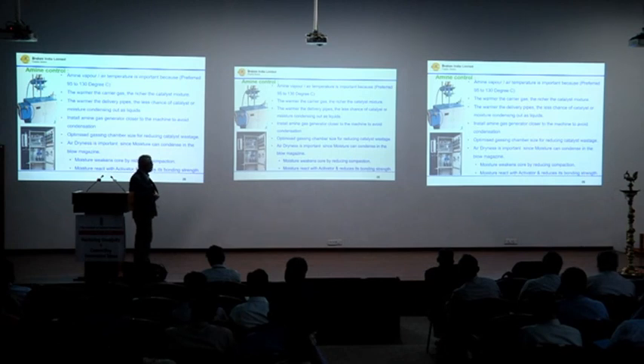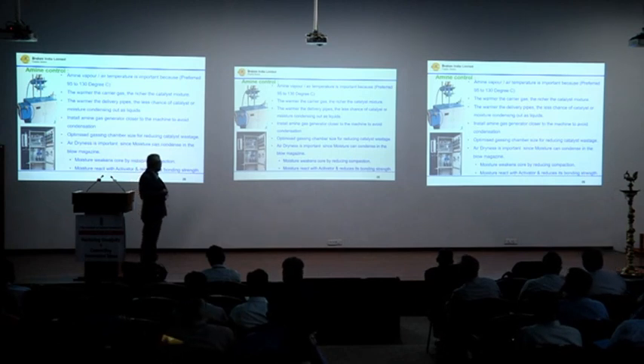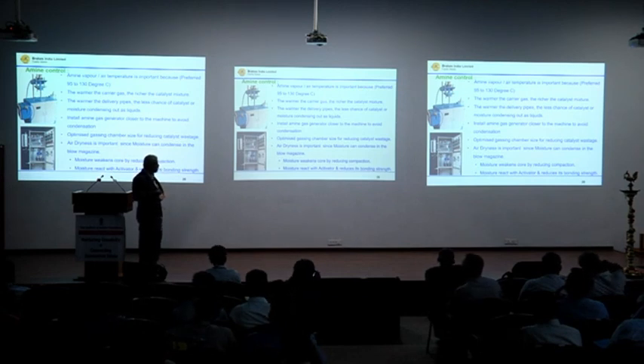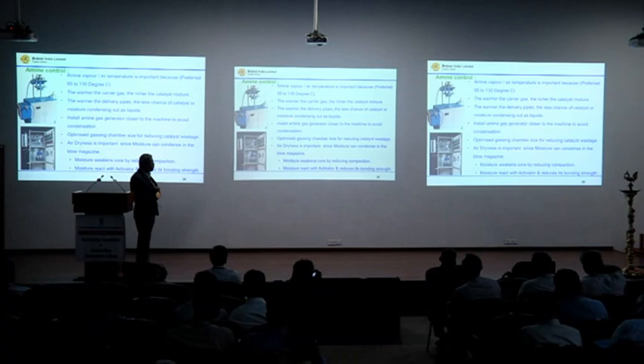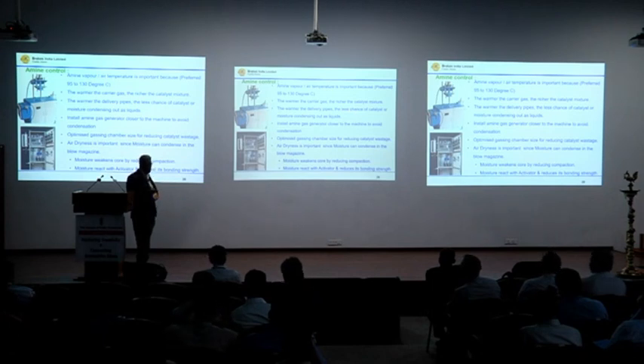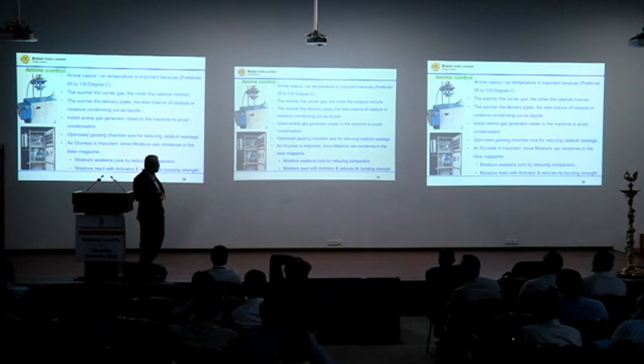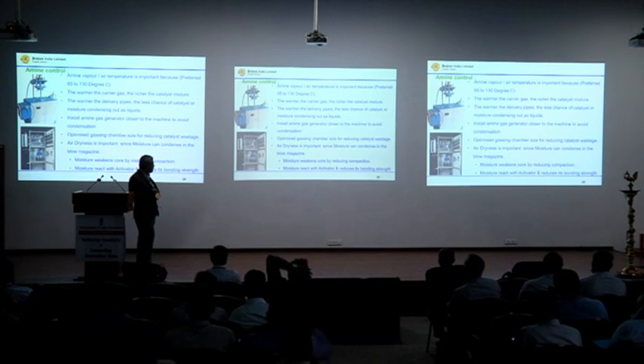So this is on amine control. Amine vapor air temperature is important to have a uniform flow of amine gas, so 95 to 130 is the preferred range. The warmer the gas carrier, the richer the catalyst mixture. The warmer the delivery pipelines, the lower the chances of catalyst or moisture condensing as a liquid. If the temperature is low, it condenses and becomes a liquid amine. So install the amine gas generator closer to the machine to avoid condensation.